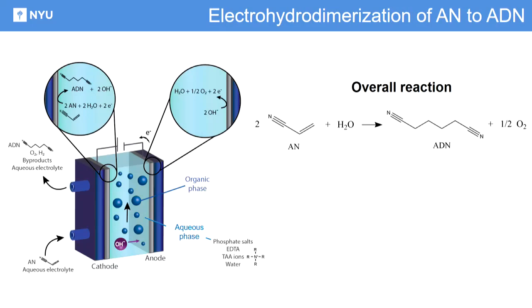So you use a cadmium or lead cathode, which I call an anti-catalyst, and you use that to avoid hydrogen evolution because you have an aqueous electrolyte. So you have an aqueous electrolyte that contains phosphate salts, EDTA, tetraalkylammonium ions, and water, of course. And then you disperse your organic phase into this aqueous electrolyte to bring your reactants and then to collect your